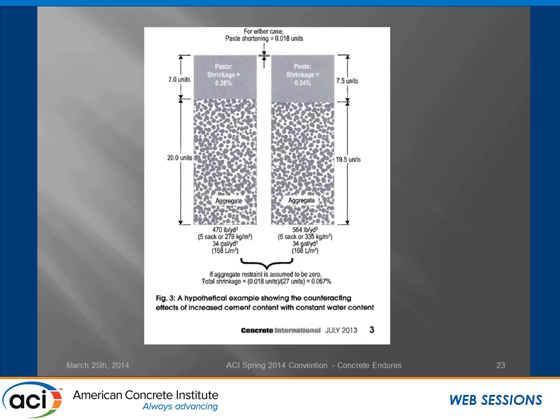So what's going on? Well, here's a graphical explanation. The one on the left is a 5-sack mix, yes, a 5-sack mix. Both of them have 34 gallons of water in it, a typical amount of concrete. And the one on the right is a 6-sack mix with 34 gallons. There's more paste in the one on the right than the one on the left. Notice the water cement ratio on the one on the left has a shrinkage value of 0.26%, which is the number taken off of that graph from real data, rounded to two decimal places. The one on the right is 0.24. Well, when you do the calculation, the cement paste portion of both of them, at two decimal places, shrinks exactly 0.018.